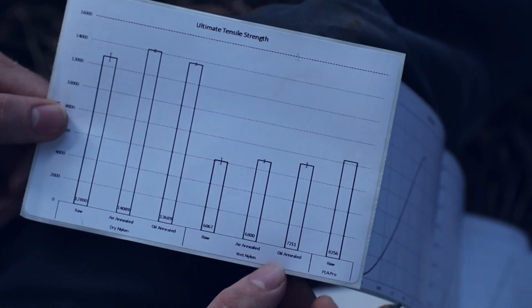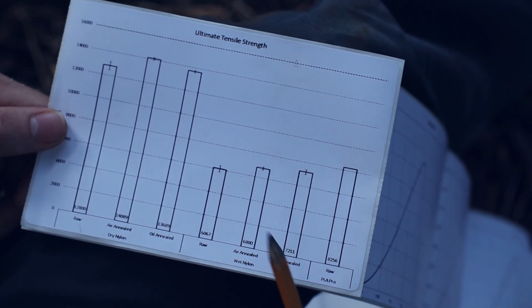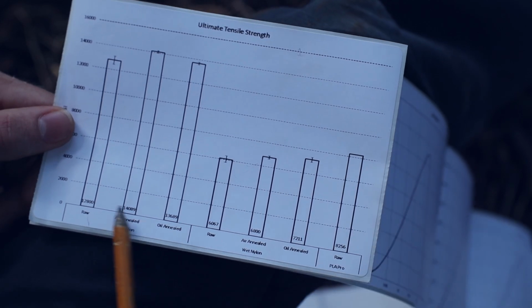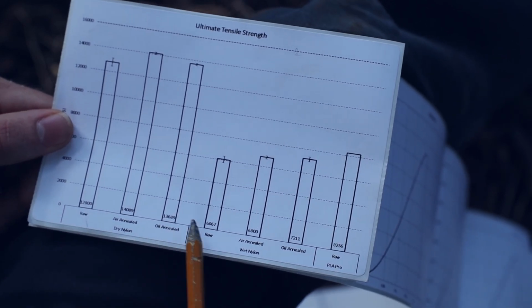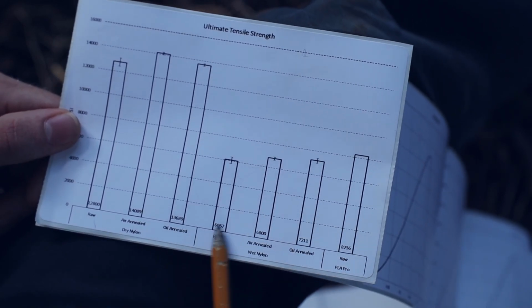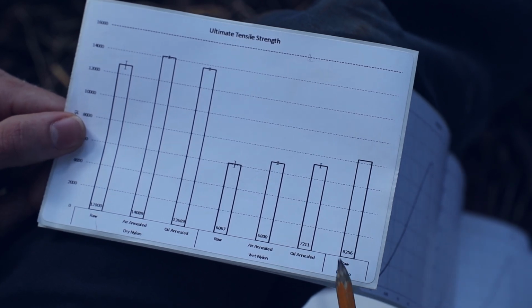Let's look at the test results. This here is where I plotted the ultimate tensile strength for all the different samples. This is the dry nylon that was kept in the dry box. This is the wet nylon that was allowed to absorb moisture. And then this guy over here at the end is the PLA Pro from Polymaker.